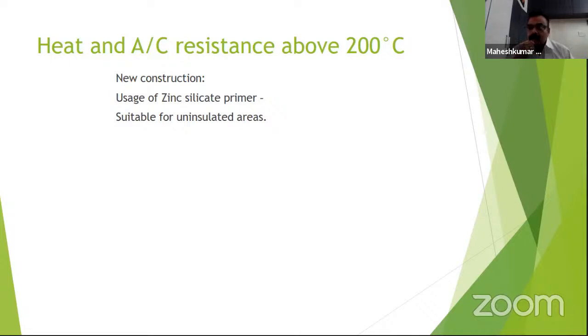Because first of all, when you use inorganic zinc silicate as a primer, it is a mortar-like structure. It has pinholes. It has voids. These voids may hold some of the moisture which is coming from the atmospheric condition. Now, if this moisture interacts with the system, then it is possible that the areas nearby may have some salinity. And this salinity can disturb the whole corrosion process.